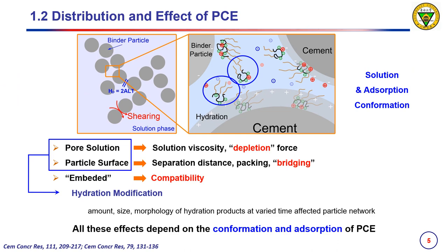As can be seen from the scheme, there are three different stages of PCE molecules in the system. First, some molecules remain in the pore solution, which enhance the solution viscosity and affect yield stress through the so-called depletion force. Second, some adsorb on the surface of a particle, which could increase the separation distance, improve the particle packing, and sometimes also induce bridging between particles.